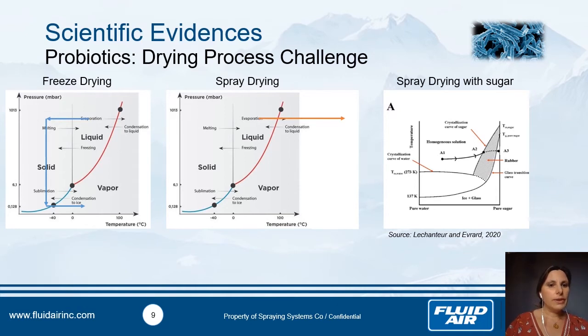So in the case of freeze drying, I just wanted to focus a little bit more on probiotics. You start at atmospheric pressure and temperature, and your first step is to freeze down to minus 40, 50 degrees C. After that, you reduce your pressure and you heat back to ambient temperature. In general, you avoid having so much damage to your probiotics. It's a process that you use when you have a thermosensitive compound. But in fact, you can have some damage due to changing the physical state of membrane lipids or the structure of sensitive proteins. So it's great, but it could also be optimized.